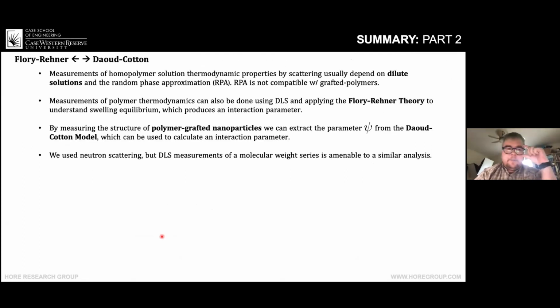So to summarize the second part, we connected the Flory-Rehner analysis of microgels using DLS with the Daoud-Cotton model that was derived for star polymers and polymer grafted nanoparticles. And I'd like to highlight a couple of points about this. The first is that when you measure homopolymer solution thermodynamics by neutron scattering, typically you prepare dilute solutions and you use the random phase approximation. You can't use the random phase approximation, as far as we know, when you have polymer grafted nanoparticles. So it's really difficult to get the thermodynamic information from polymer grafted nanoparticles.